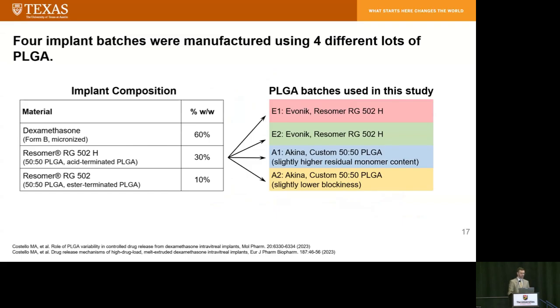We manufactured 4 batches of our reverse engineered formulation using the process that I explained earlier. These 4 batches were the same in terms of every meaningful variable, except we used different sources of PLGA in each batch. So for the 502H, which is the primary PLGA excipient, we used 4 different batches of PLGA, 2 from Evonik, which is the same material as in the brand name, and 2 batches of PLGA that were custom synthesized by Akina to be slightly different in these properties.